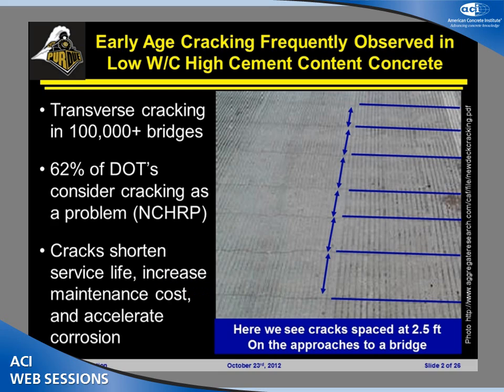I think we're all in agreement that there are potential issues when we start getting cracks in the structures. This drives the point home: currently there are over 100,000 bridges that exhibit transverse cracking. 62% of the DOTs consider early cracking to be a major problem, and a lot of this cracking is occurring long before these bridges are ever even trafficked. The real issue is that the cracks are going to shorten the service life, increase the maintenance costs, accelerate the corrosion, and mean that we're replacing these decks more frequently than we really need to.